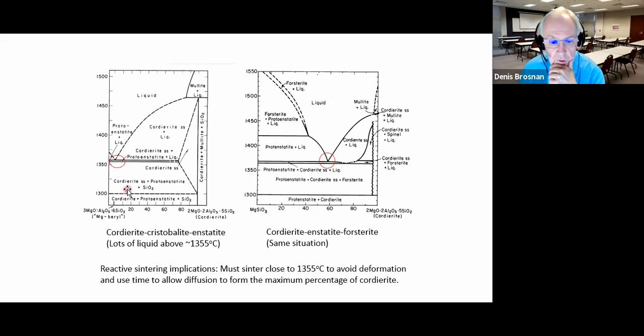Now, here are sections of the 3-component diagram, and I like to look at these because they are pretty easy to look at. Here we've got cordierite. You can see a peritectic here. So once you heat above the point at which liquid forms, above the peritectic temperature, you'll have a solid phase plus a fair amount of liquid immediately. So generally in the older technology, you didn't want to go above that peritectic unless you had played some games with the composition, because you'd have all of a sudden too much liquid and you would indeed begin to have some melting in the ceramic.